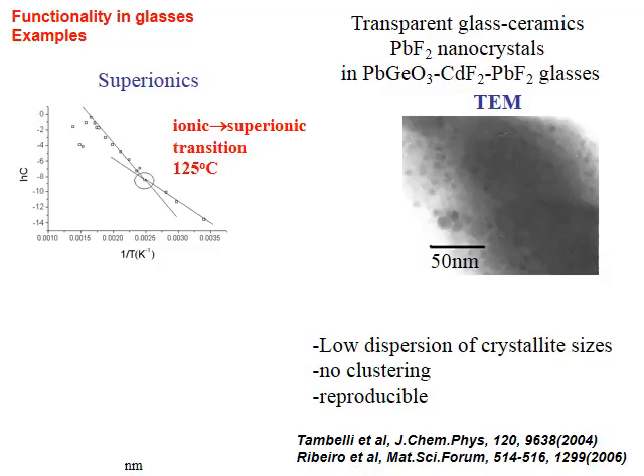The transition ionic-superionic can be easily detected in a conductivity measurement as a function of the temperature. This figure shows the results for such measurements for a transparent glass ceramic in this system. Results are shown in an Arrhenius plot. Ionic to superionic transition is easily identified at 125 centigrades. We call attention to the fact that Tg for these glasses is located at much higher temperatures, around 350 degrees. At 125 degrees, the solid behaves like a liquid, as concerns conductivity.